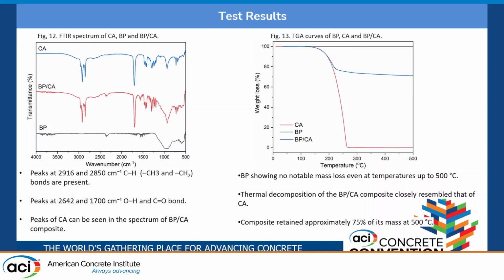And as we look at the TGA, we can see the basalt powder has no mass loss up to 500 degrees. And for the capric acid, expectedly, we are losing all of its weight up to 260 degrees Celsius. But when we incorporate this PCM into our supporting material, we are retaining 75% of our mass, and it shows us that this is quite a thermally stable material.